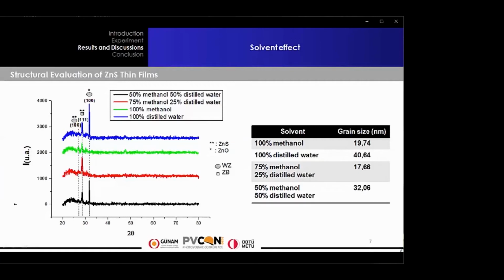Note also that wurtzite ZnO peaks were clearly observed for two solvents, 100% distilled water and 75% methanol, 25% distilled water. This result indicates that all ZnS samples have a zinc blende structure and the sample grown in 100% methanol also contains a wurtzite structure.